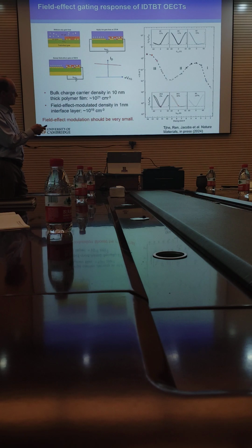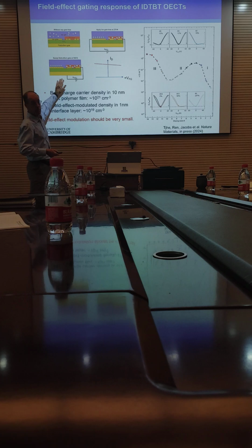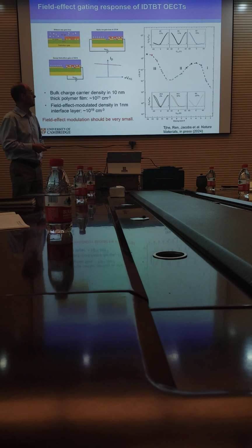So this is the transfer characteristics that I've already shown you, with the peak in the conductivity, the valley, and then this regime 3 due to HOMO-1 conduction. And in the insets, you see the characteristics of this device when measured at low temperature, where the ions are frozen. And then you see how the current depends on the FET gate voltage, the bottom gate, the voltage applied to the silicon gate.